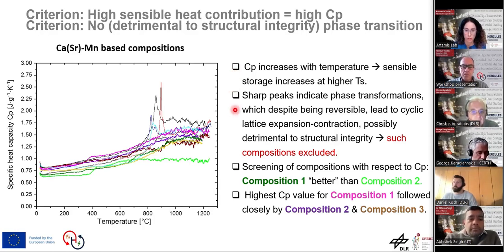Some compositions are characterized by sharp peaks, which indicate that as we heat the material, a phase transformation happens, which might or might not be reversible, but even so, we don't want it because it possibly leads to detrimental expansion and contraction and affects structural integrity, and so such compositions are excluded. And of course, such graphs are a merit of materials versus each other.